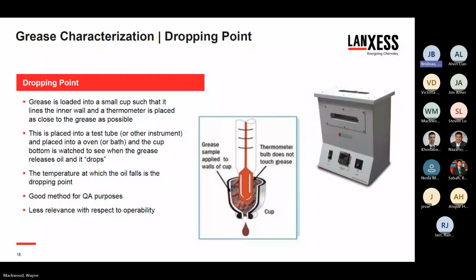Basically, a very thin film of grease is heated up, and we look for the first sign, or the first drop of oil, to fall at the bottom of the beaker that it's held in. That is called the dropping point. And then there's a little calculation to relate the temperature of the block versus the temperature that you measured, but you end up relating it to what's called the dropping point, and it's basically the temperature of that drop of oil.